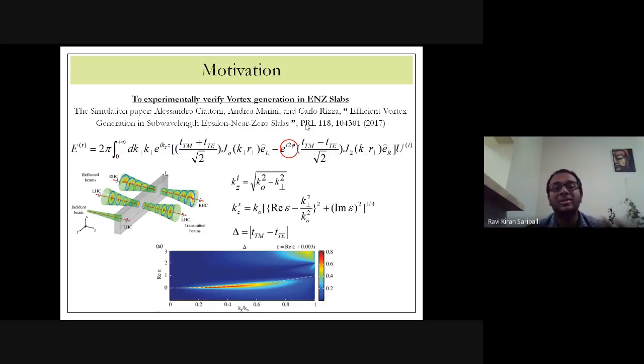So this was the motivation of our work, to experimentally verify the simulations that people did in 2017 to show this ENZ phenomenon where you can see a spin orbit interaction. They come in with a left circular polarized beam, and the incident beam is a Gaussian. But in the right circular polarized beam, you can see that there is an OAM, or orbital angular momentum, which is generated. And what they show, which is a remarkable result, is that you come in with an input paraxial beam, unlike any other case that was previously reported. You always had to come in with a non-paraxial beam to start seeing spin orbit interaction. But here you come in with an input paraxial beam, and you start seeing this spin orbit interaction.